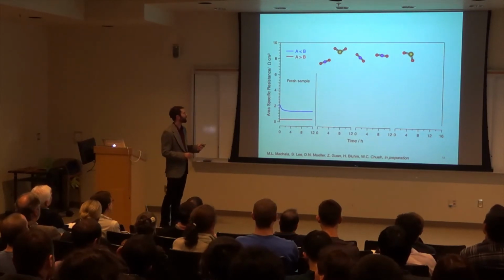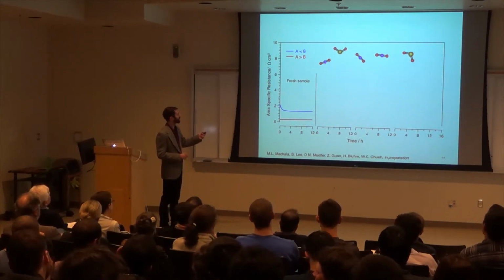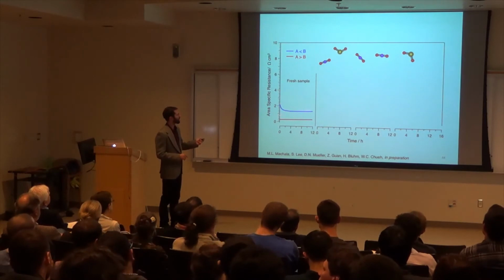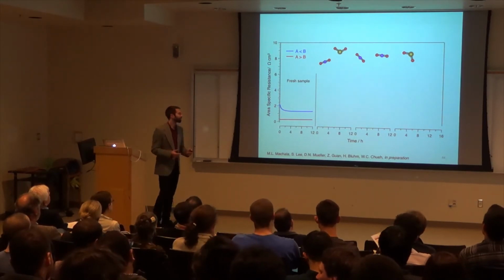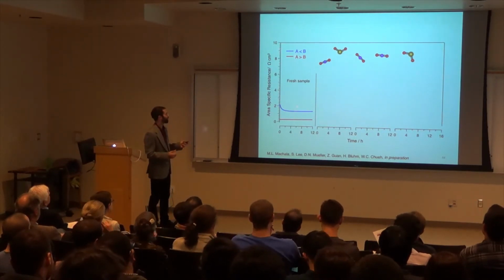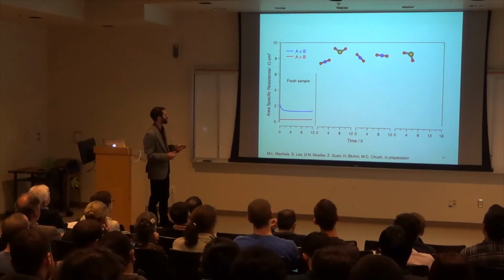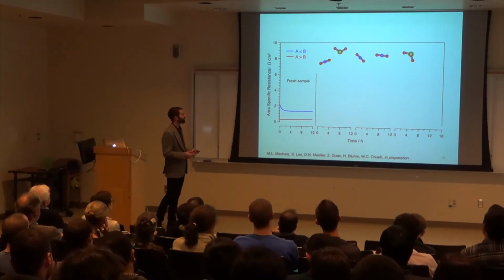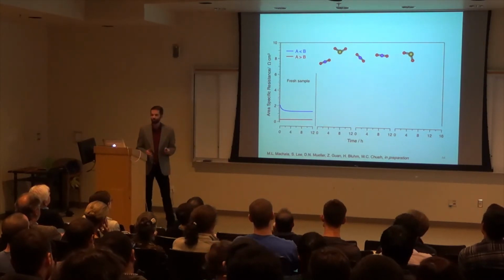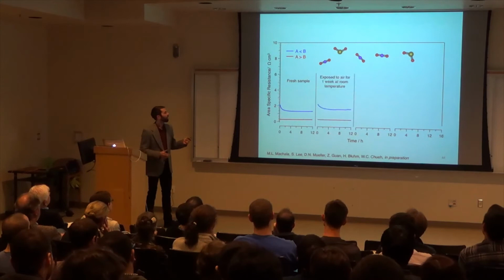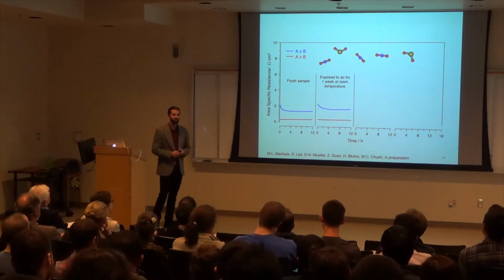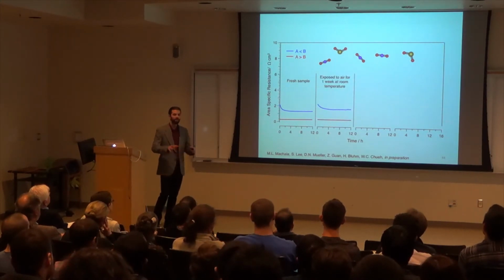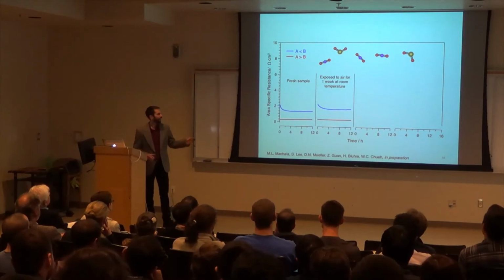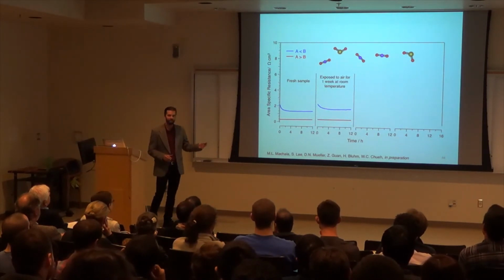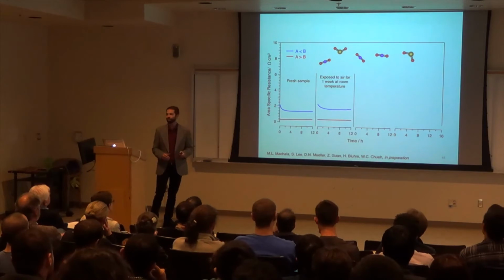The first thing that we do is we take one of these materials each, and we test them. We want to make sure that they're operating as we expect. We have the A-site deficient here in blue, and in red we have the A-site excess. And this is the resistance, how good of a catalyst it is, as a function of time. This fresh sample is in a very clean environment, relatively stable. We then expose it to air after testing in 1 week. We let it sit at room temperature to see if anything happens. And what we saw was that not much changed. So at room temperature, not much is actually happening.